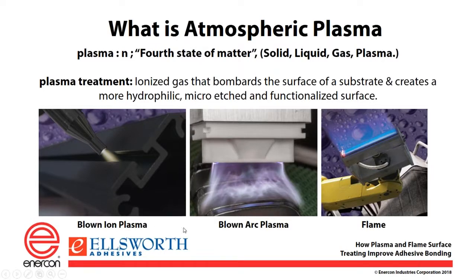So we have three different types. We have the blown ion plasma that you see there, which is a line of sight, or excuse me, a direct type of discharge. We have the blown arc plasma, which is similar to a blown corona. It has a wider nozzle. It can go out to 2 or 3 inches. The speeds have to be a little bit lower. It doesn't do quite as well with the cleaning as the blown ion or the flame of the surface, but there's a lot of applications, especially print applications, where blown arc is a good alternative.